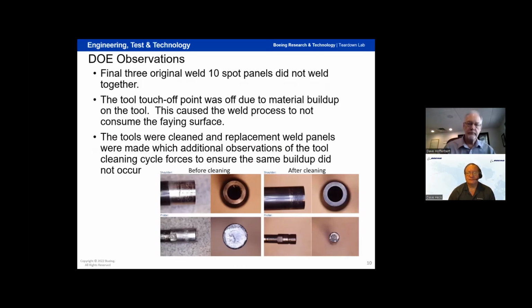So, as mentioned a couple of panels back, we did have to do 3 repeat panels. We were doing these in rapid succession, one after another. We did get some buildup on the tools, which caused the touch point to be off. This is doing research and trying to push it into full scale production really fast. You see some things like this, but we were able to go through a procedure and see what the tools look like, both cleaned and before they got cleaned. But we could do this in process as well. So those final 3 panels were able to be run without any issues, just running some additional cleaning trials on the tool itself in process.